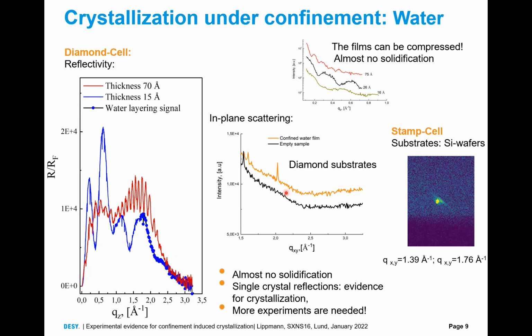If we talk about crystallization, we do observe single crystal peaks in the confined samples of water in both cells, in the diamond cell and in the stamp cell. We compare these results with samples which we call empty samples. It means that we close the gap or confine the substrates without the liquid inside. This ensures that the peaks we observe are coming from the liquid confined in the substrates. Moreover, the Q values at the positions where we observe these peaks cannot be assigned to the crystal structure of the substrates. Therefore, we believe that the peaks we observe are coming from the crystallization of the water.